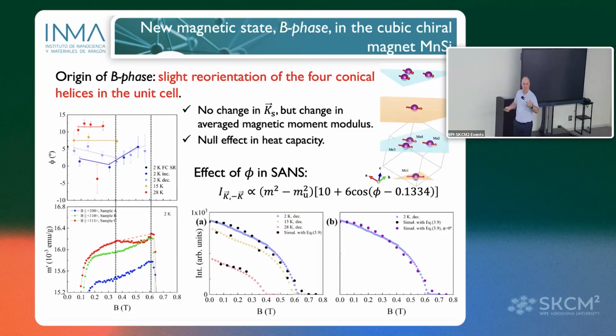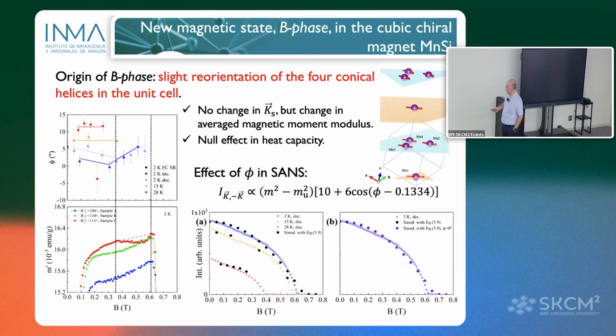And then if we want to calculate theoretically the intensity of the SANS as a function of the angle, we see that the rotation angle is producing a very small change in the intensity, not visible in our experiments. The theoretical calculations are the black points. But we are able to fit our SANS curve very well with this expression.